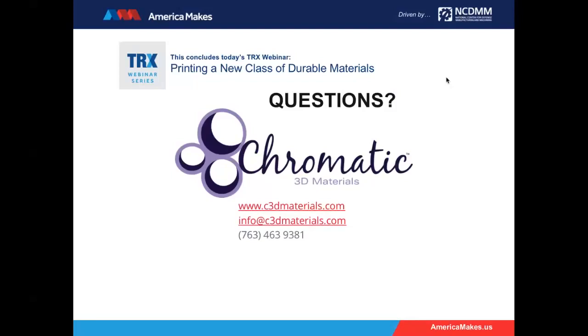I think another attribute of the urethanes is that they are paintable. Paint adheres very well to urethanes, as well as the embedded color like we demonstrated. And then another really nice attribute of urethanes in particular, and a lot of thermosets, is that they are millable. And so you can certainly imagine a case where you can print, say, a multi-material part and then finish off with milling and get a very good surface finish that's quite common in the milling area, where you can get to very high resolution and definition.